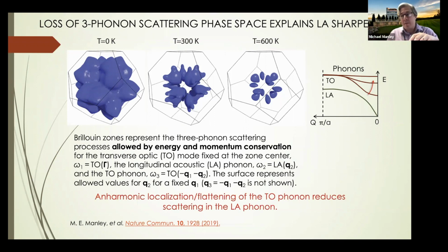But in this case, I asked Ole to do these calculations for me. So he calculated all the combinations of the transverse optic phonon that's moving most, the one at the zone center, and all the scattering conditions for that mode and the LA phonon. So you create 3 phonons, any TO phonon, any LA phonon in any direction with the 1 TO phonon at the center. And then that TO phonon is now moving. And this is captured by the simulations. And then what he does is he calculates what is the phase space for that scattering process. And this picture that he made represents everywhere in the zone where the 3 phonon scattering processes are occurring. And what happens is as you raise the temperature, this phase space basically disappears.